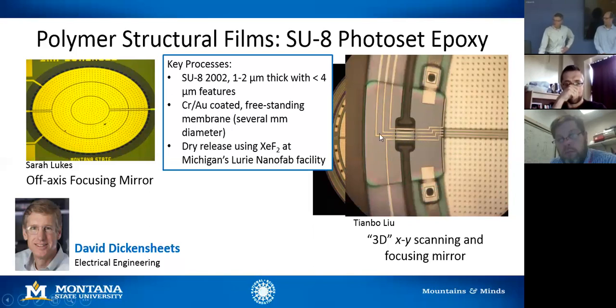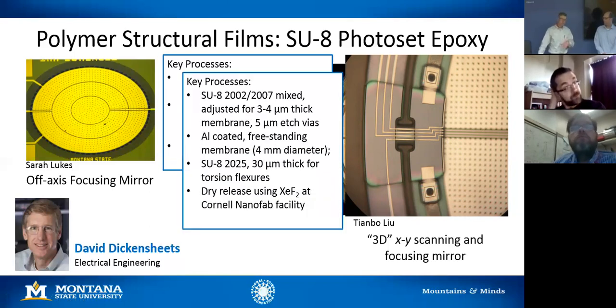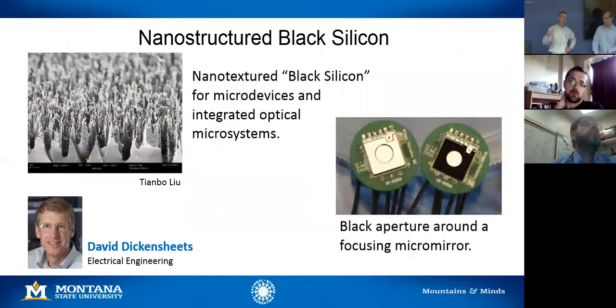This hinge has electrical contacts coming across, but this is a mechanical element. This also is SU-8, but in this case, it's thick, 25 micron or 30 micron thick SU-8. So this shows the types of features we can get with this particular material system and the expertise that we have in-house to support this kind of fabrication. For this device, in addition to these various thicknesses of spun cast SU-8, we also did a xenon difluoride etch, but this time at Cornell. So we go where it's convenient and where we can get access, and we can help users understand where they might go to get these processes done.